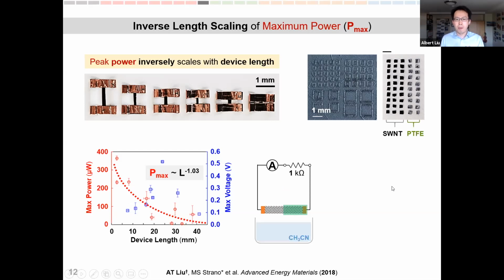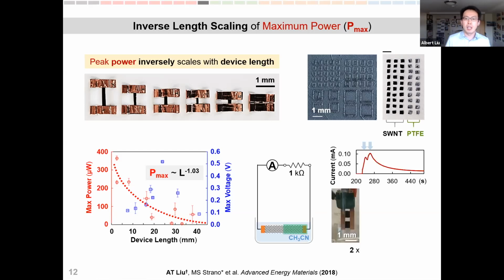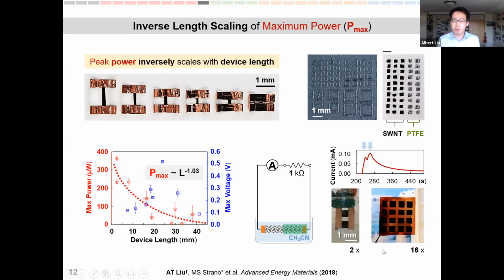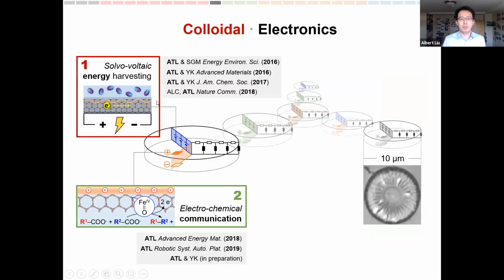In doing so, we can just immerse this Janus particle uniformly into a beaker of acetonitrile, and that generates the electricity for us to drive energy harvesting. As you can see, current production is accompanied by uniform immersion of the particulated devices into a beaker of acetonitrile. Our fabrication method is scalable and can be pre-patterned into different configurations for integration into colloidal electronic applications. So that concludes the first section of this talk, which is energy harvesting using a solvo-voltaic-driven method.